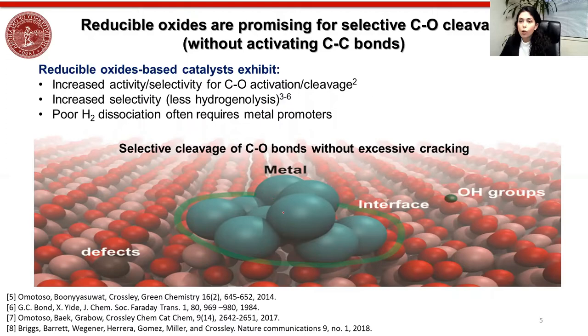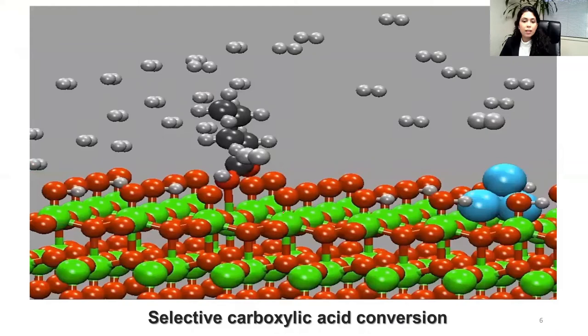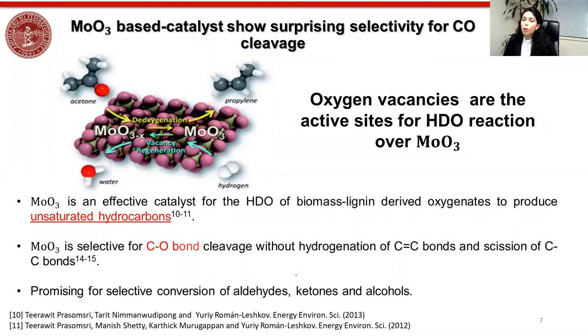The role of the metal promoters is to split the hydrogen, which spills over at the surface and creates zone defects or exposes cations that can be active sites for different types of chemistry. We decided to study molybdenum oxide catalysts because Professor Yuri Román at MIT has shown that acetone can be converted to propylene over molybdenum oxide, meaning this catalyst is very good at breaking the C-O bond without saturating the C=C bond. We have also shown this catalyst is very selective for the conversion of aldehydes, ketones, and alcohols. However, it has not been used before for the conversion of carboxylic acid, so we are interested to study whether unsaturated products can be obtained.